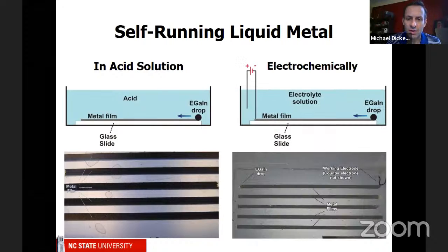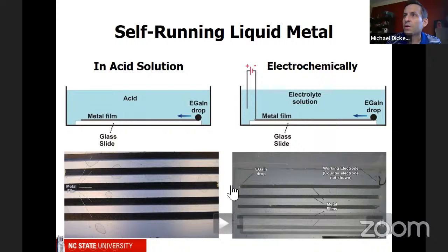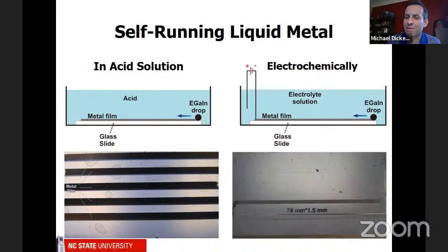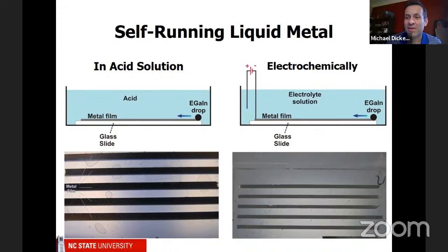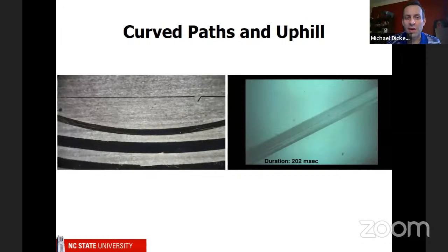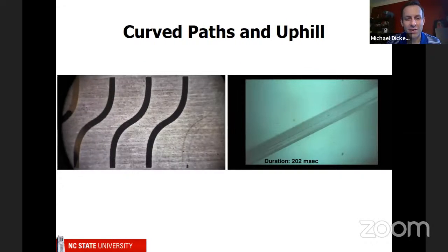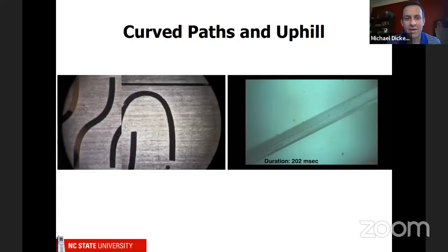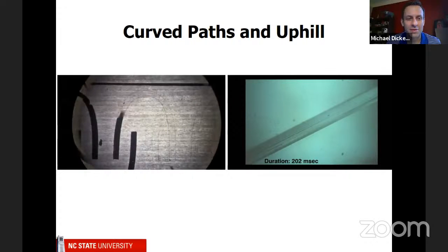You can also do this using electrochemistry. So if you look over here on the left, you'll see that there's a droplet of liquid metal. Here's an electrode, and as soon as we apply a voltage, we can remove the oxide and it will zip right along. And it's very fast. So we can do this on curved paths to get it to follow different paths. It will go around a circle. And we can even make it go uphill.